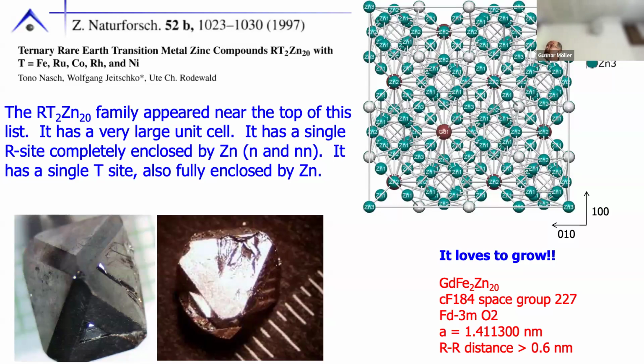So why doesn't iron have a moment in this case? It doesn't. In most intermetallics, especially dilute ones, transition metals tend to drop their moment. Actually getting transition metal magnetism in intermetallics takes effort. In many of the 122s, rare earth nickel 2 germanium 2, nickel's not moment bearing. Rare earth iron 2 germanium 2, the iron's not moment bearing. So that's not unusual. But we'll get back to this question in just a moment.